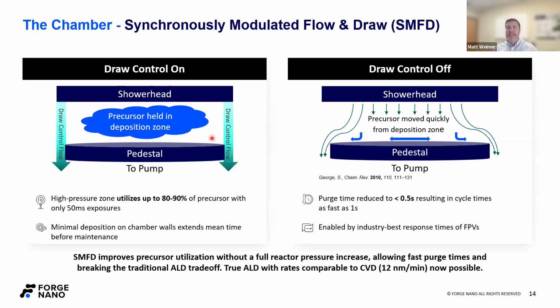Again, that SMFD, we're a single wafer ALD chamber, so not batch, single wafer, have that shower head design, but we encapsulate our deposition zone with a nitrogen gas curtain. We call it a draw control. And essentially what that draw control does, it allows us to access the high pressure regime and the low pressure regime each when we want them, right? So that trade-off I was talking about before, we get the benefits of each regime while avoiding the detriment. And so, we have this little cloud here that shows we're holding the precursor when it's on, and then when we turn it off, the precursor flies out of the chamber.